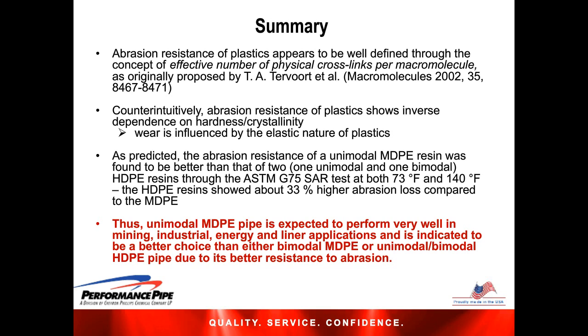I think that's exactly right, the abrasion is dependent on many things, as you just stated and as we mentioned earlier. I would say, though, that in terms of the effect of just velocity, it's well established and well known that the higher the velocities, the higher the abrasion capacity of the abrading material. But in terms of the relative response of the 2708 to 4710, I am not aware of anything that would suggest that the 2708 shouldn't continue to outperform at the higher velocities. That would be my response.